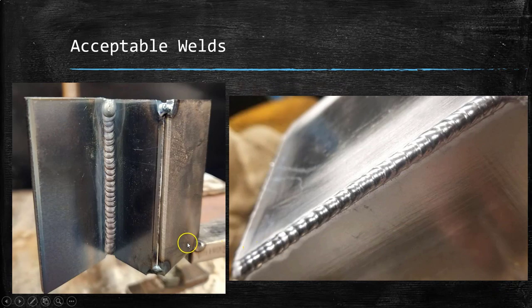And this is what your welds should look like when your parts, when your tungsten, when your metal is free from any potential contaminants. Now, there aren't any grind marks on this metal because it's cold rolled. It just has that discoloration from the heat of the weld. This person went over the material with a wire brush before welding. And so you can see that there are no discolored spots in the weld. There's nothing brown. There's no presence of scale, contaminants. Doesn't look like the person dipped their tungsten into the weld or anything like that.